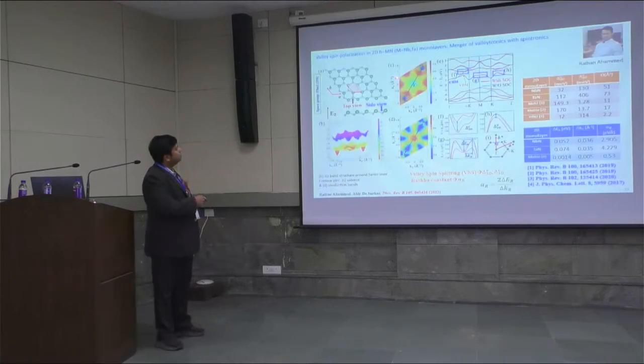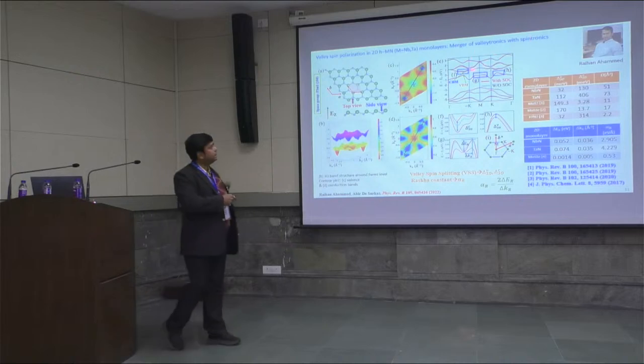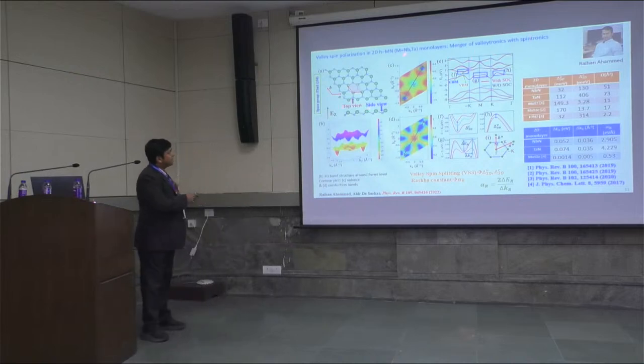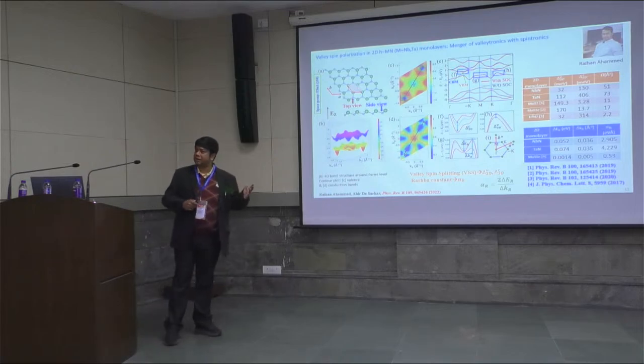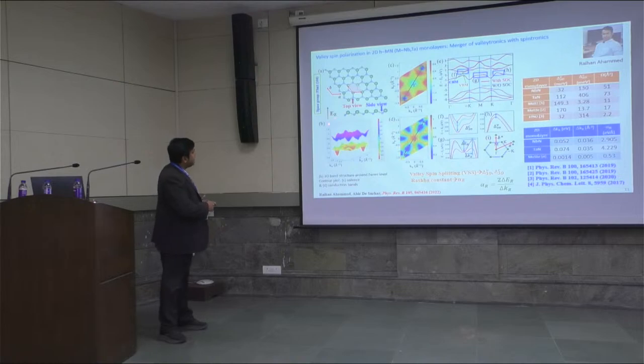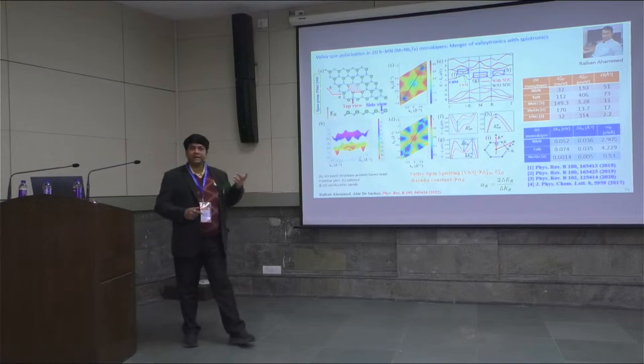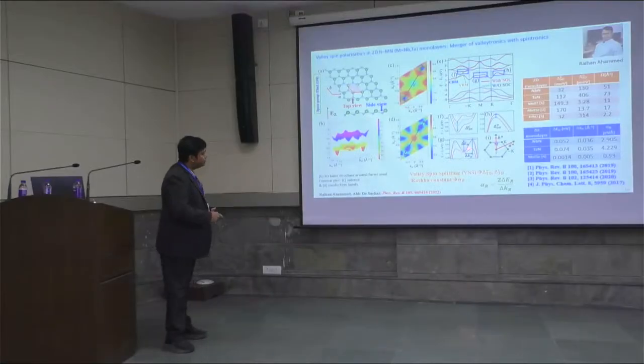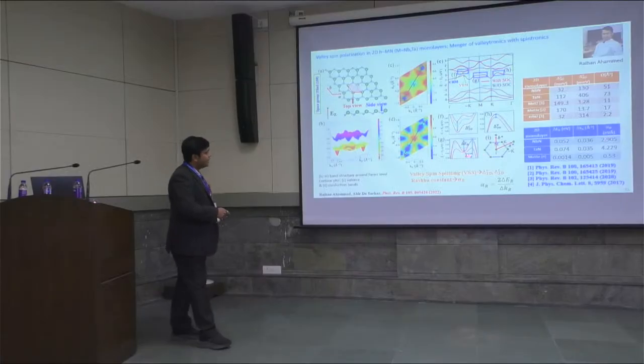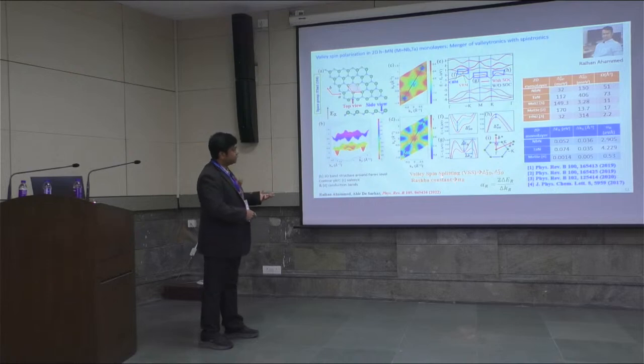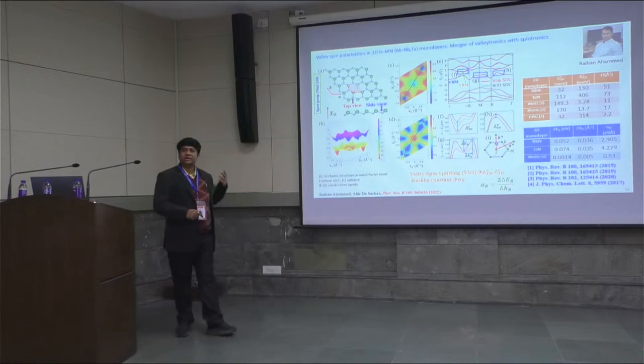So then moving on, we have also proposed these monolayers for the integration of valleytronics with spintronics. This niobium nitride monolayer or tantalum nitride monolayer has a hexagonal honeycomb lattice and a polar buckled structure. Because of the polar buckled structure, an out of plane electric field intrinsically arises in it, which induces momentum dependent spin splitting. And that gives rise to a Rashba constant.